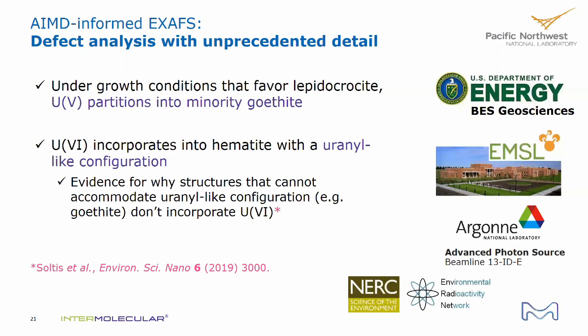So we have within a cluster a few dozen scattering paths. We have a few dozen coordinating atoms in what we would maybe classically call the first, second, third, and so on shells. In each case, that would be calculating the phase shift from these different elements, but there's still only a single uranium absorber within the structure.